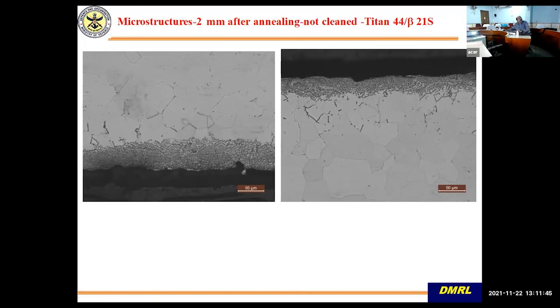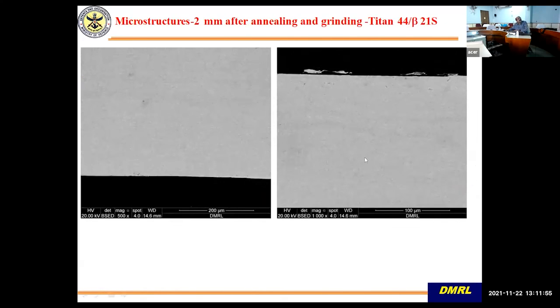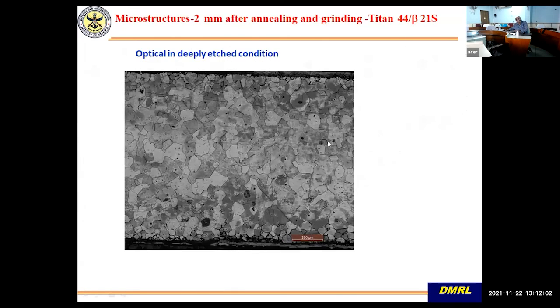And then the other problem was on the sheet, when you heat treat, you start forming oxide layers which look like this. That you have to remove by proper procedure, which was done. Again, your single phase material is beta treated, so that is why you are not seeing any contrast. So this is the deeply etched condition, optical.